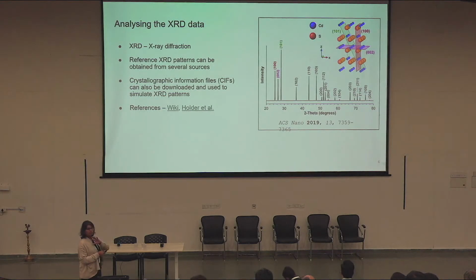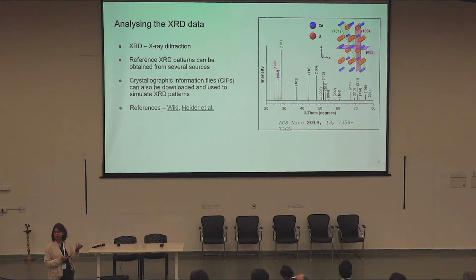Now, let's say I do the XRD of a particular material, and then I get this particular plot. Here, the sample that was taken was a cadmium sulfide crystal. If you look at the cartoon of this material, there are different possible crystal planes present. The interplanar distances between different kinds of crystal planes are going to be different. So based on that, you are going to get the scattered beam at different theta, that is the angle of incidence.